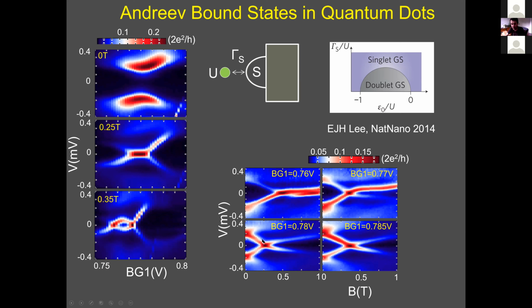So generically, what we have as a function of magnetic field is this resonance. Zeeman splits, one of the branches goes down, one goes up and above the gap. And there is a point at which we have a 0 bias peak. Now, this 0 bias peak is quite different from Majorana because it's intermittent. It's just from a crossing of 2 levels. It's momentary. It is not stuck for a long time at 0 bias.